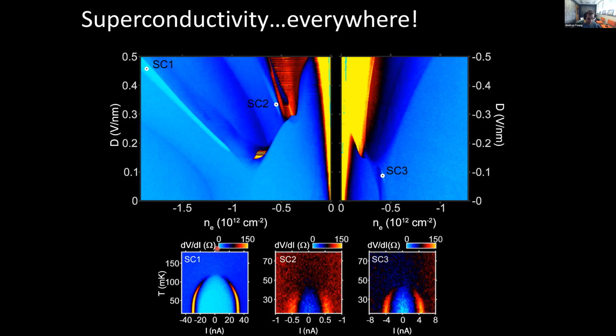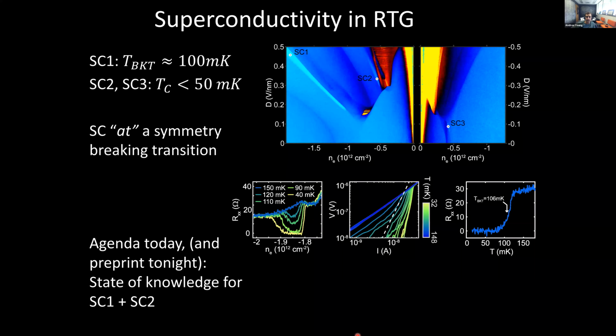Okay, you can see this through the nonlinear resistivity dV/dI, which drops either to 0 or very close to 0 at low temperatures. They're all superconducting below 100 millikelvin. The weakest ones maybe only below 50 millikelvin. They all show this onset of nonlinearity and zero resistance, or near zero resistance in the case of the least well-formed one, which grows with decreasing temperature. And they are all, as you can already see from transport, basically tightly correlated with phase transitions in this ground state, isospin magnetic order.